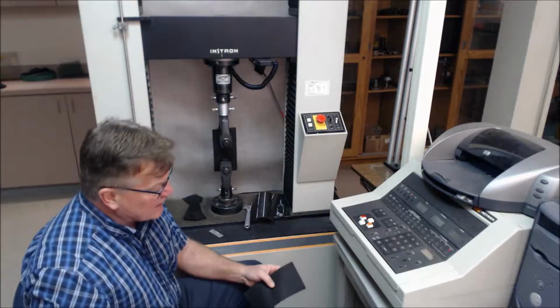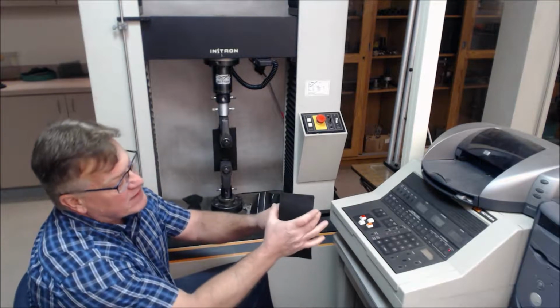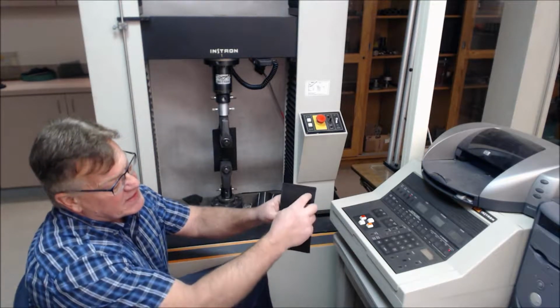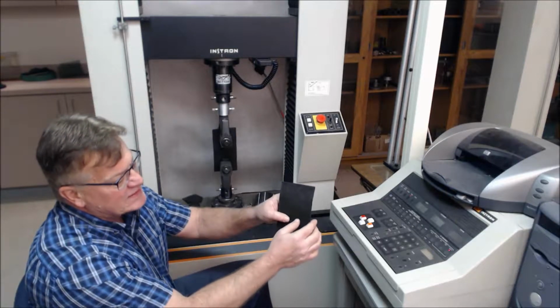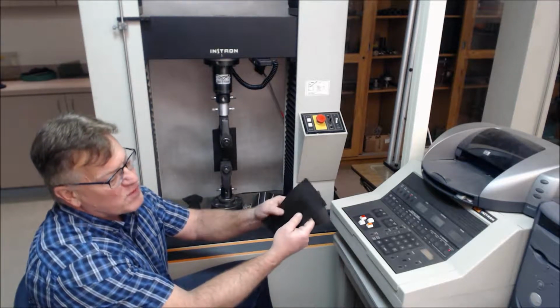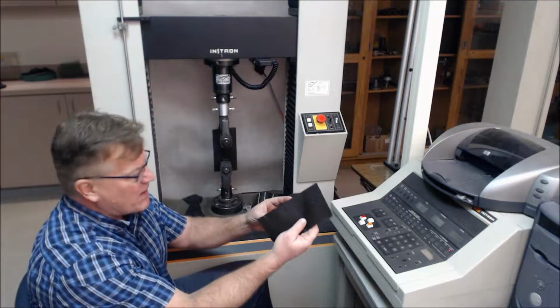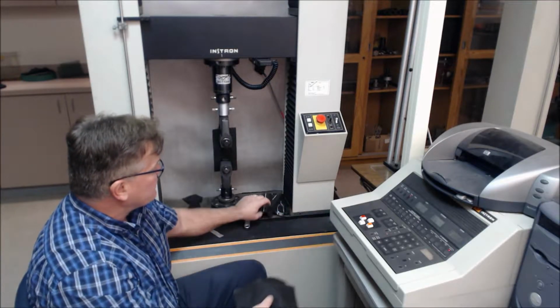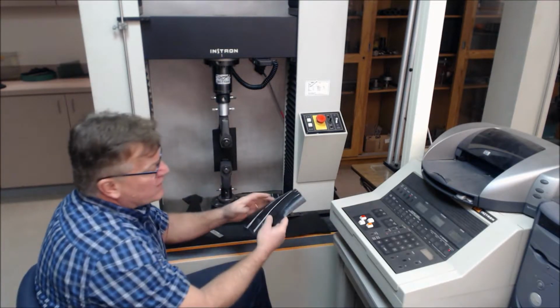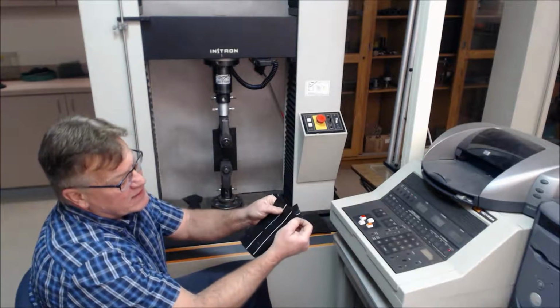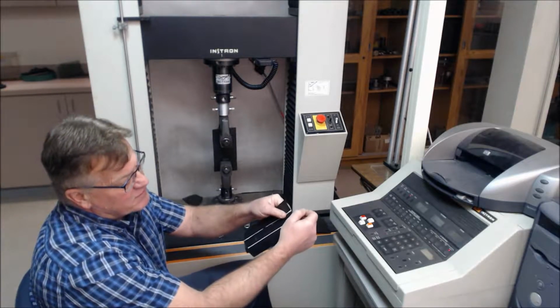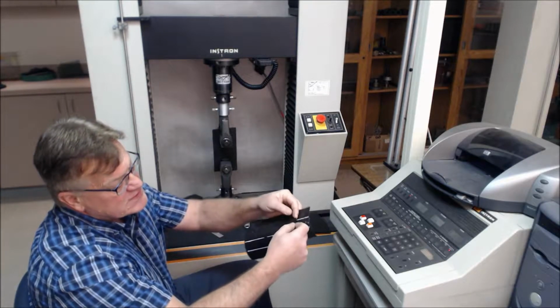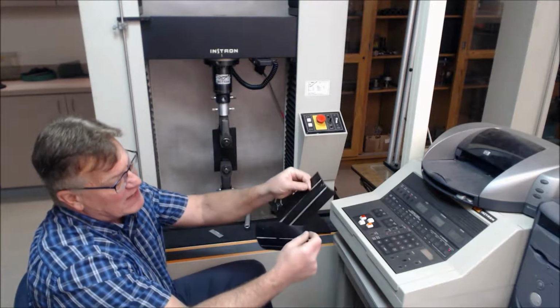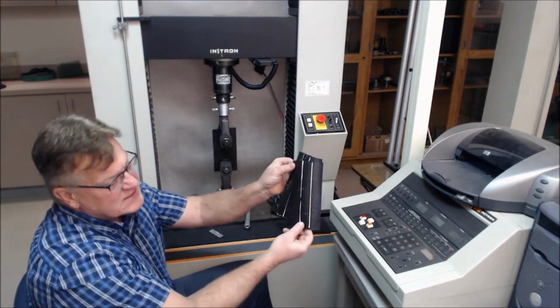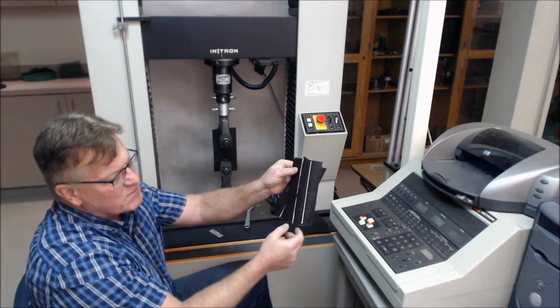clicker press. You would like to cut out specimens that are 100 millimeter by 200 millimeter in length. So it's a 4 by 8 inch rectangular specimen. These are the non-woven, these are the woven. The woven, it's very important that you orient the direction of the fibers. You can see that they're very much aligned in this case, in the machine direction, and it's also marked.